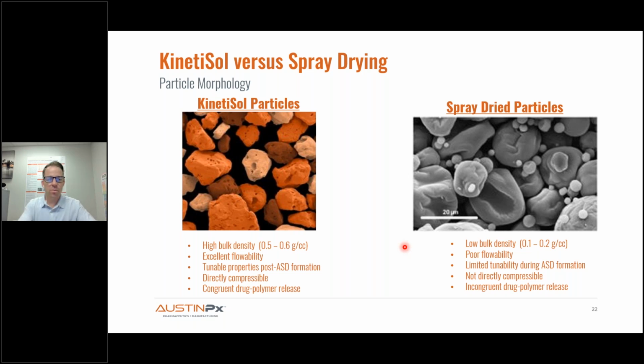So now let's look at particle properties. Kinetisol particles are pretty similar to melt extruded particles because the particle properties are influenced downstream of ASD formation. So we form the ASD, we make this molten mass, we've got this glass disc that I just showed, and then we use the downstream milling technology to engineer the particles. Now that's a really distinct difference from spray drying. It's similar to melt extrusion, but it's a very distinct difference to spray drying, where the particle properties are dictated by the ASD formation process. So there's not as much control.